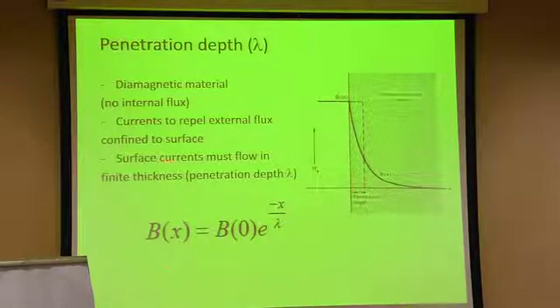So this is how the magnetic field varies inside a superconductor, and for very large x divided by lambda, of course, the current goes exponentially to zero. So this is the first characteristic length in the superconductor, the penetration depth. It relates to the circulating supercurrents which create the opposite magnetic field, and also to the length scale over which the magnetic field drops to zero from the applied external one.